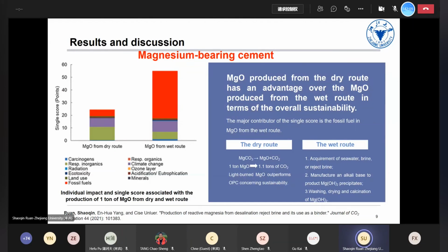You can see from this figure, the left one, MgO from the dry route, has a lower single score compared with the MgO from the wet route. However, in terms of the dry route, the major magnesite production country is China. So if you want to use MgO from countries other than China, transportation is needed, and it will also lead to some environmental impacts concerning the transportation of MgO.